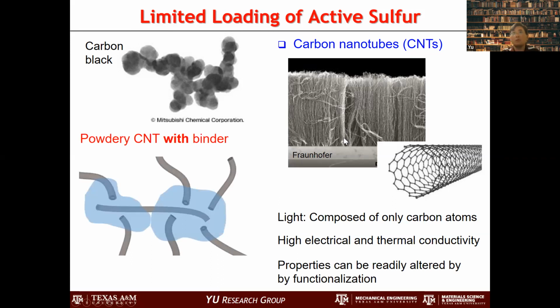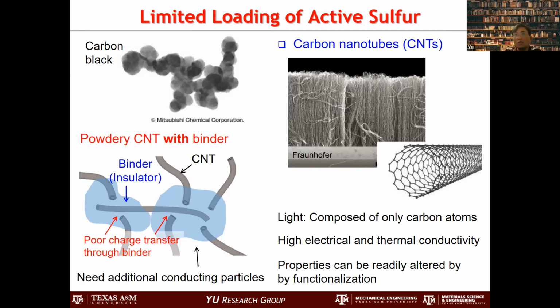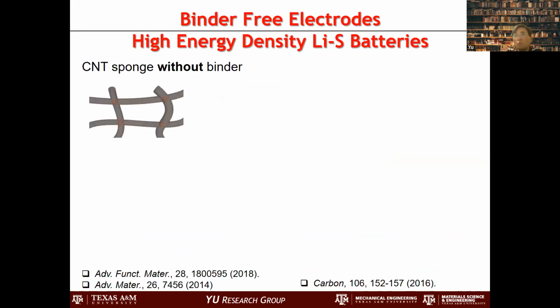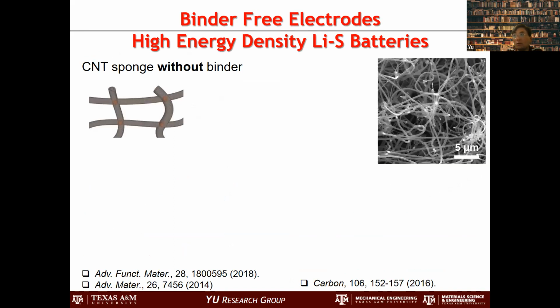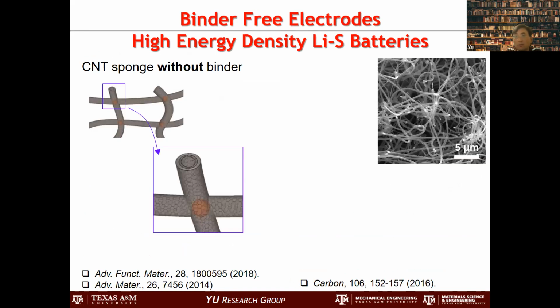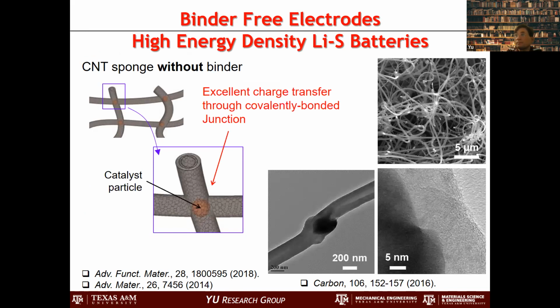But the problem is, if you just buy commercial carbon nanotube, it is powdery, so you have to use a binder to glue them together. The problem is that this glue is insulating, and then the electrons cannot transfer. That's the problem. Then you need to add more conductive additive, and as a result, this becomes problematic. So what we are actually doing is making carbon nanotubes that are connected in this fashion. It's basically a 3D structure, so they are all connected without too much trouble, and we don't need a binder. Like this way.